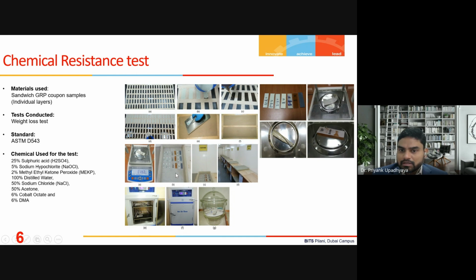So these are the boxes that are prepared where we have filled these chemicals, and these are all the chemicals lined up here, and then we expose these samples individually in these. So there are 6 layers, so you can see 1, 2, 3, 4, 5, 6 samples are there, and 1 sample there is which is the composite as a whole. So the standard that we are following for this test is ASTM D543.